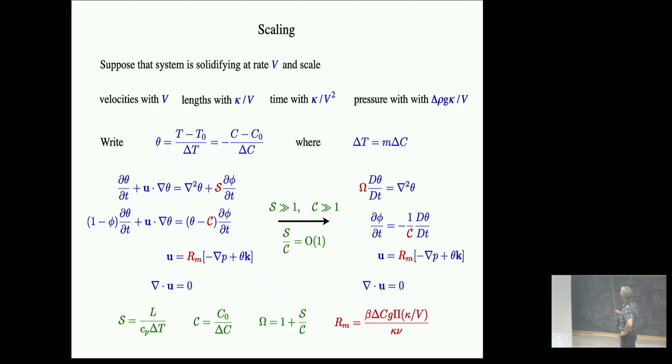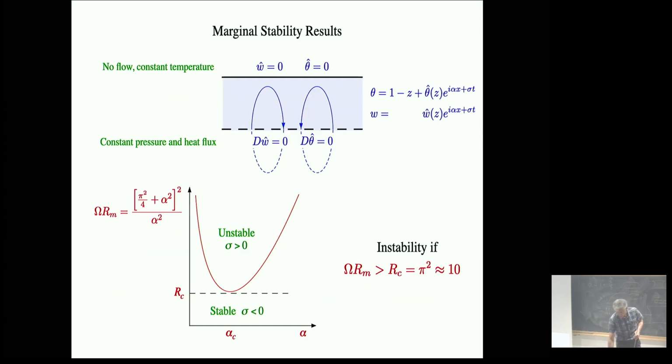Actually, let's think of it the other way around. We're less prone to convection if we have small Stefan number. And that's because at small Stefan number, I can melt really easily or dissolve really easily. Okay? And remember, it's that dissolution, that interior dissolution, that dissipates buoyancy. And so at low Stefan number, I will dissipate my buoyancy more easily, and I'm less prone to convection. So we can understand some physics out of a reduced mathematical model. It's useful for that sort of understanding.